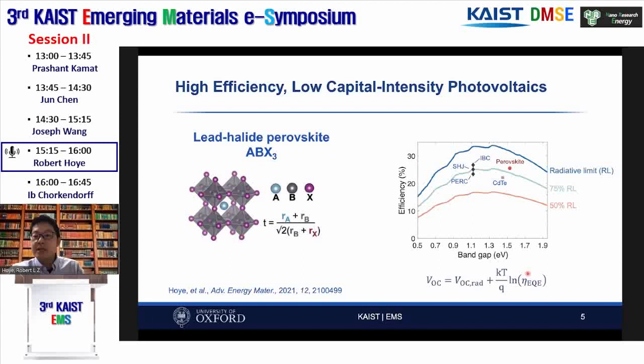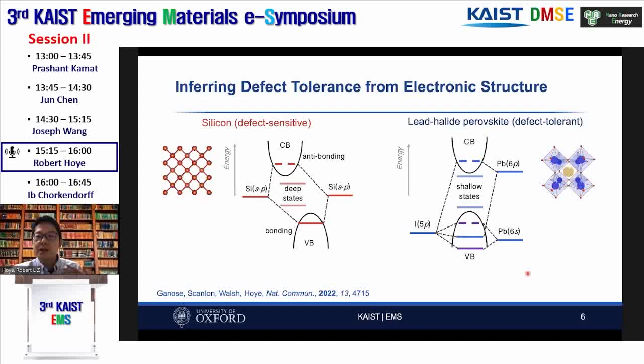And indeed, perovskites make exceptionally good light emitting diodes as well. They're very good emitters. And that seems quite surprising, given that the perovskites are made using much lower temperature, very simple processing routes, and have higher defect densities. Because historically, you would think that to get a low non-radiative recombination rate, you have to get rid of the defects as much as possible.